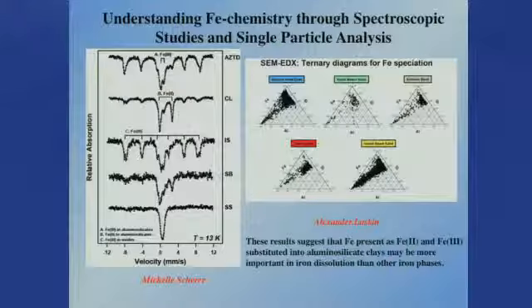Our colleague Michelle Scheerer does Mössbauer spectroscopy. She was able to identify iron(III) and iron(II) in aluminum silicates, as well as iron(III) in oxides such as hematite. That was really helpful in narrowing down some of the speciation of the iron. And then we worked with Alex Laskin to look at the maps of the amount of aluminum, silicon, and iron. These are ternary plots. What came out of our data analysis is that iron(II) and iron(III) substituted in aluminum silicate clays was really the most important in terms of the bioavailable, the most soluble iron. So combining spectroscopy with single particle analysis was hugely helpful.